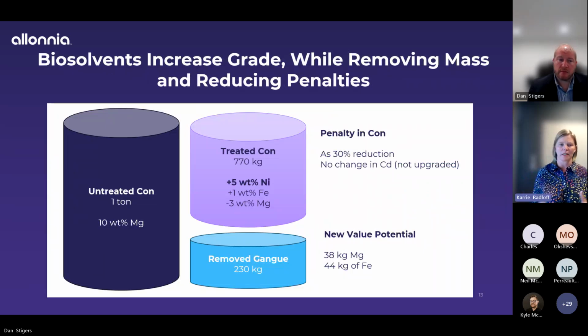So when we start to do this, we want to do a mass balance, right? So what we're seeing in our reactions, thinking about that 20% loading figure I just showed you, is if we started with 1 ton of untreated con that has about 10% by weight magnesium in it, what comes out of our process is a much smaller volume, just under 800 kilos, but we've upgraded that con so that it's got a 5 weight percent increase in nickel, just a 1% weight increase in iron, and a 3% decrease in magnesium. So that means that you're shipping less material with much higher grade and less of the problematic elements of magnesium. So at the smelter, this allows you to put more material through, so you're not having to limit capacity.